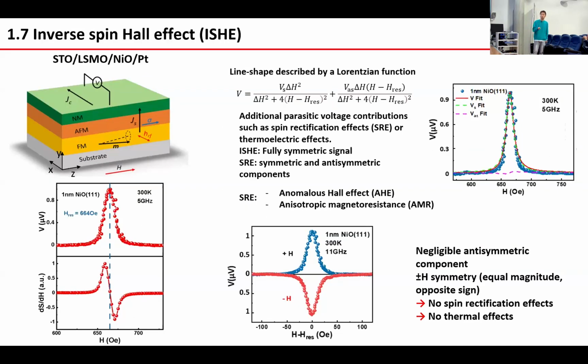And let me introduce the inverse spin Hall effect. As I mentioned before, once the magnetization excites the spin current, it transfers through the antiferromagnetic layer and reaches the normal metal, and a detectable electric voltage can be achieved via the inverse spin Hall effect. In the real measurement, we can measure simultaneously the inverse spin Hall effect voltage and the ferromagnetic resonance absorption peak. And in this case, we show that the resonant field is quite similar, at the identical position. This shows that the inverse spin Hall effect comes from the spin pumping.